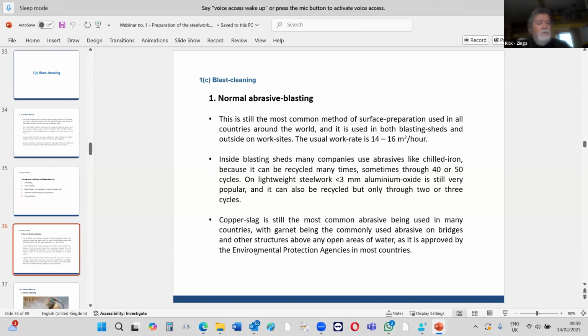We've had some companies saying, "Oh, chilled iron, if we use normal black slag, it's 100 euros a ton, for example, and chilled iron is 450 euros a ton." I said, okay, according to the new laws, all blasting slag that's been used is now classified as toxic. So you buy 50 tons a month of slag. When it's used, you then have to bring in the truck to take it away. You're paying for 50 tons to be taken and dumped in the landfill every month. So there's your costs already going up, okay?